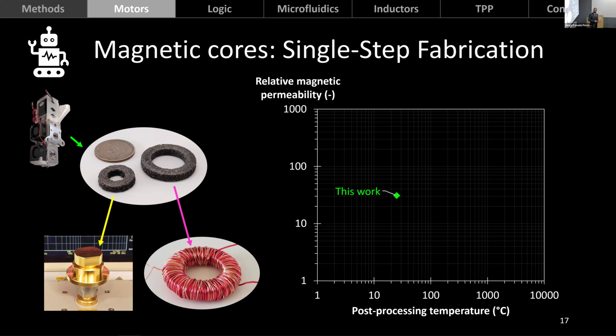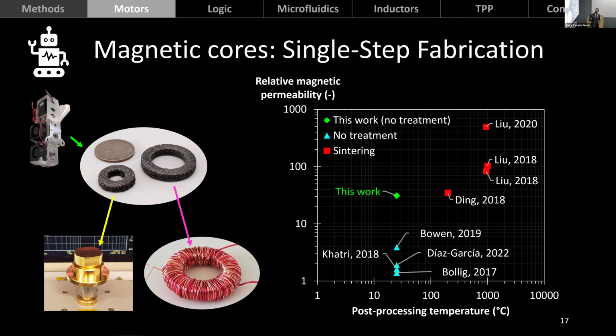Now, is that good? Well, if we compare it to other 3D printed cores that don't rely on temperature post-processing, then we can see that we are outperforming those pretty significantly. But there are other ways to get higher permeability, mostly by means of post-processing at around 1,000 degrees. So higher permeabilities are possible from 3D printed cores. The thing is, we don't really want to do that because if we keep in mind that we want to keep this technology compatible with multi-material fabrication, and in particular, we might want to keep it compatible with polymers, then we can't treat it at 1,000 degrees because any polymers that we put through that temperature are going to burn.